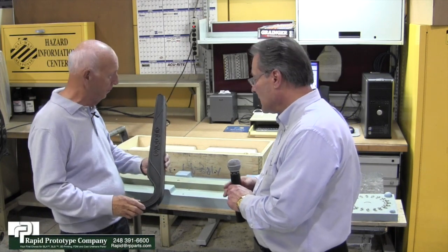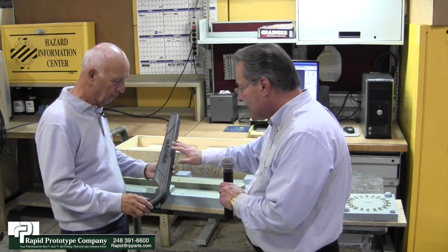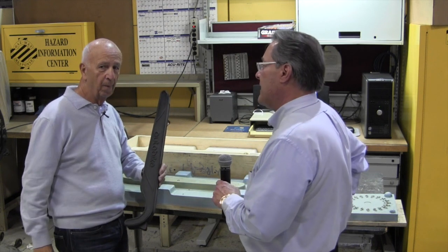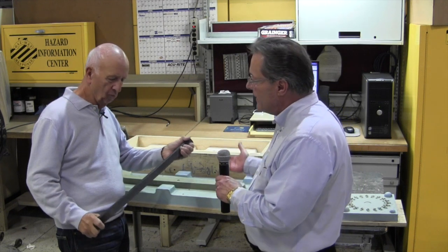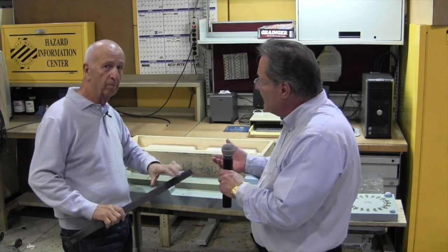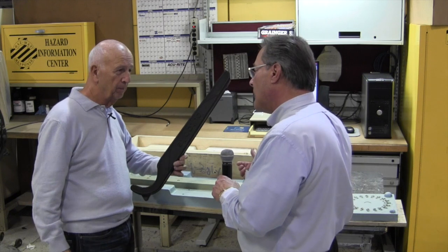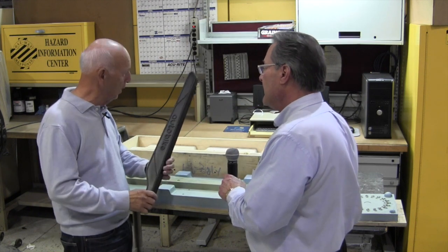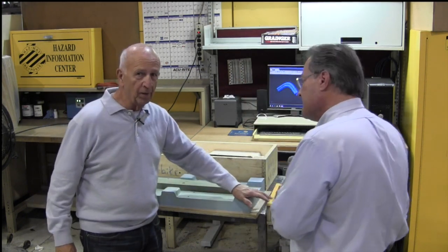Here's an example of a part that came out of this hybrid fiberglass and silicone mold—that gives you an idea of what the finished part looks like and what the tool looks like. It's got to be trimmed and finished. We put a little bit of texture on the pattern when we built it, so as the part comes off the tool it has the production texture the customer wanted. This is a Shore D urethane material, approximately 65 durometer—a mid-range material and a very popular, good all-around durometer.